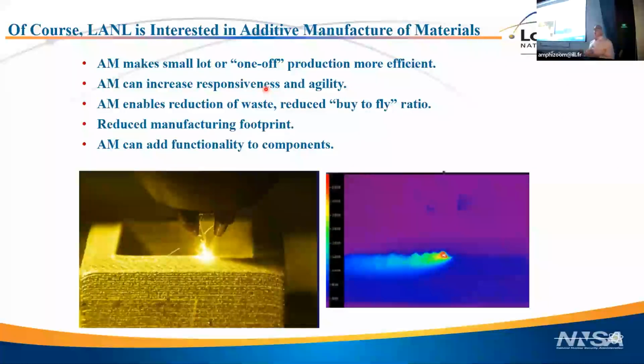It enables reduction of waste. The buy-to-fly ratio is much smaller, right? If you think about making airplane parts out of titanium, quite often you might use 15 kilograms or more of bare titanium to make a 1 kilogram part. Well, when your materials are very expensive, which a lot of our materials are, you don't want to accept that buy-to-fly ratio, and often additive gives you a way to reduce that.